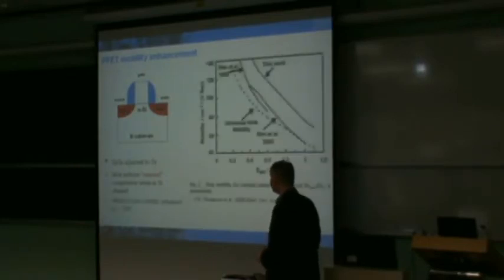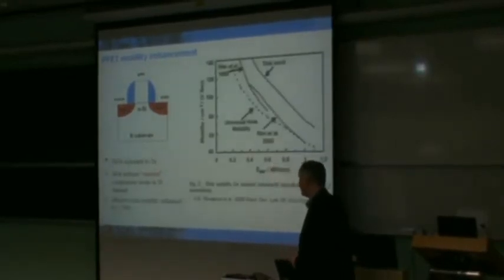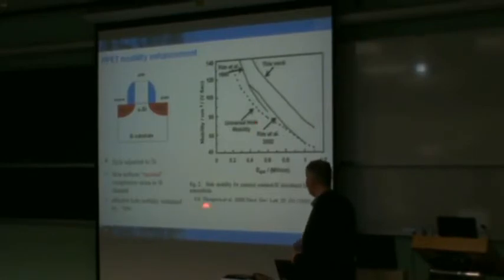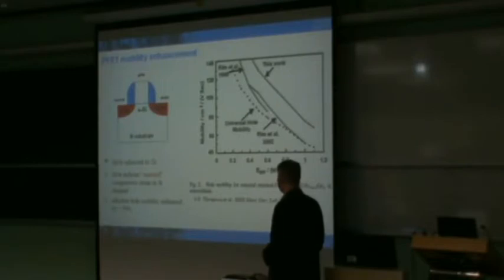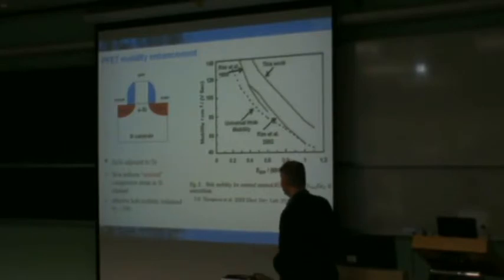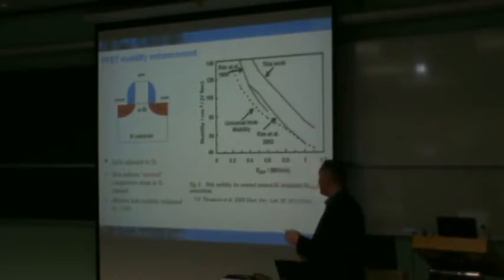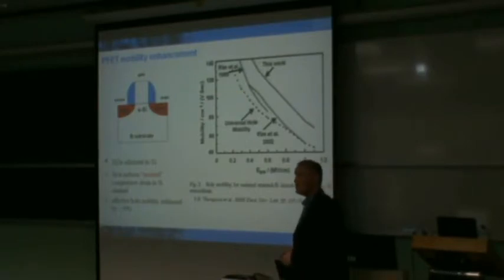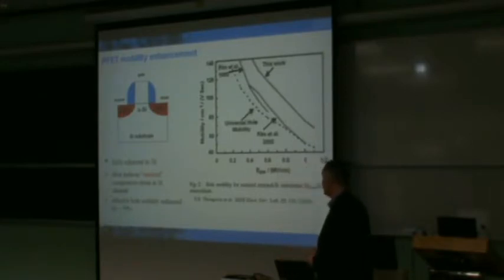Now, the key aspect is that even though this implementation by Scott Thompson in 2004 showed very clearly that you do get an increase in mobility, in this case it was enhanced maybe about 50% or so, really the benefit of using this technique with P-type transistors is that the intrinsic mobility of the PFET is much lower than that for NFET. And so this represented a huge knob in terms of boosting performance. So the values here are roughly about 4 to 5x that one could expect a mobility enhancement if the engineering and the strain was done in the correct way.